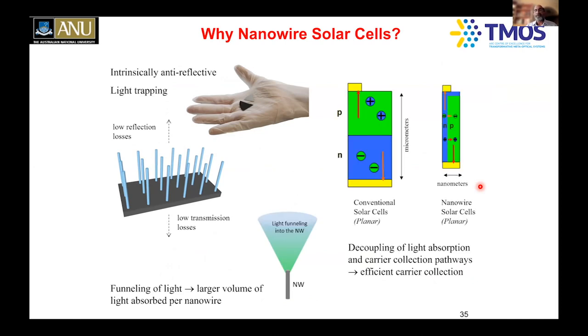With solar cells, all of you know about these things: you create a PN junction and make it thick enough to absorb all the sunlight. And then the carriers need to migrate long distances because the contacts are at the top and the bottom. But it turns out in the case of nanowires, you can make a core-shell nanowire, where you can have, for example, a P-type nanowire in the core and an N-type shell on that one. So thereby carriers can be collected very efficiently. Light is absorbed this way, carriers are collected this way. For the first time, you're able to decouple light absorption pathways and carrier collection pathways.